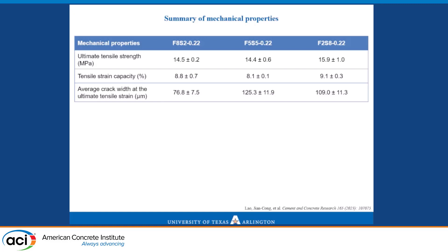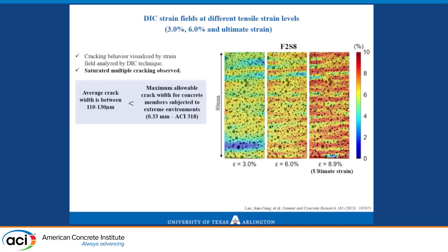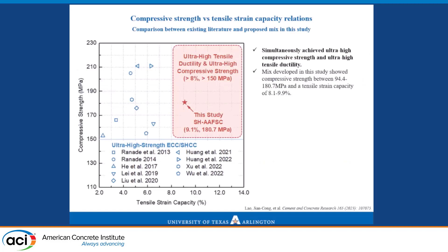You can see pictures showing saturated multiple cracking at around 9% strain, with very fine crack widths. So we now have a geopolymer that is more sustainable, and with synthetic fibers you can get high strength and high ductility. This is the last slide — a comparison of compressive strength versus tensile strain capacity. To the extreme left are all the steel fiber results; the other arm shows synthetic fiber results; and our work is shown in this study. We do not have as high a compressive strength as conventional UHPC, but we have very high ductility. This is very interesting for many structural applications.